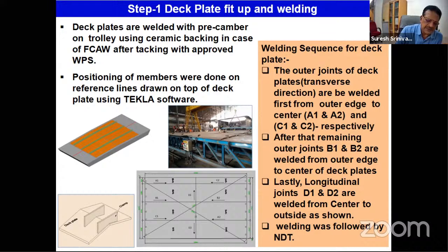We could not use it for predicting the sequence, as for this structure, if you want to run an FEM analysis, we estimated it may take about 15 to 20 days. So that much time was not available. So we used this software for predicting the shrinkage, and then with my analytical method, we predicted the sequence and ran the sequence in the mockup. Once we got very good results, we applied it straight away to the actual structure.